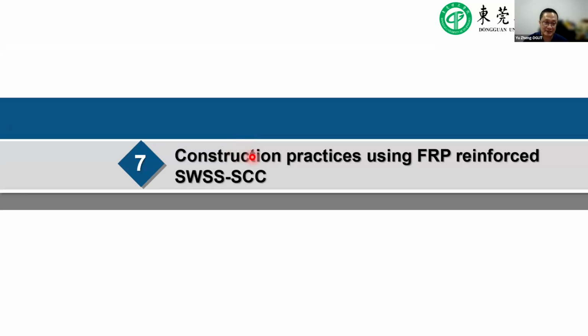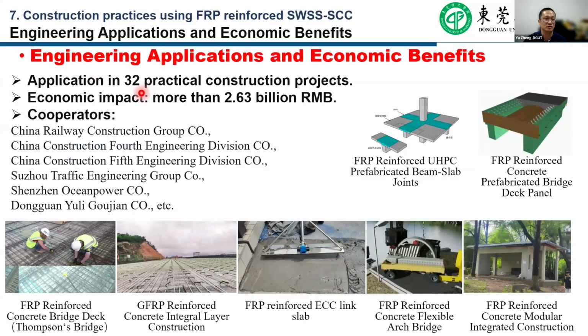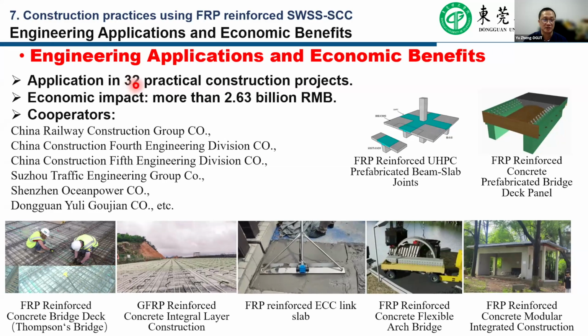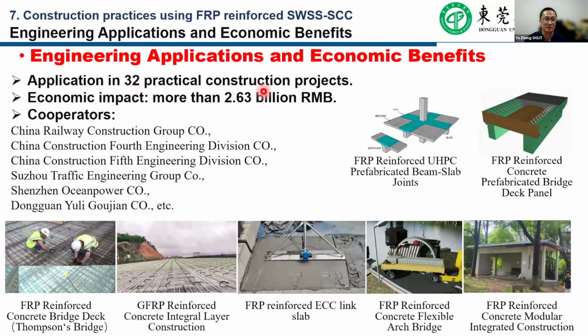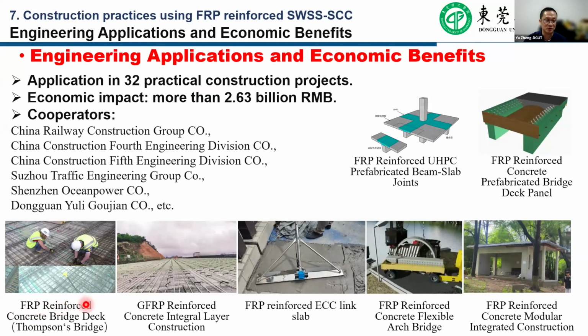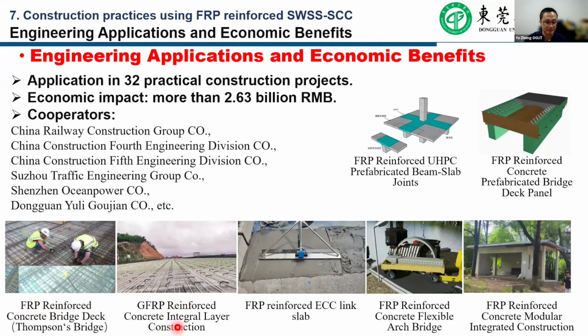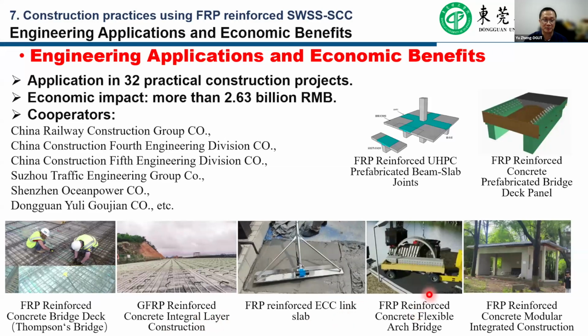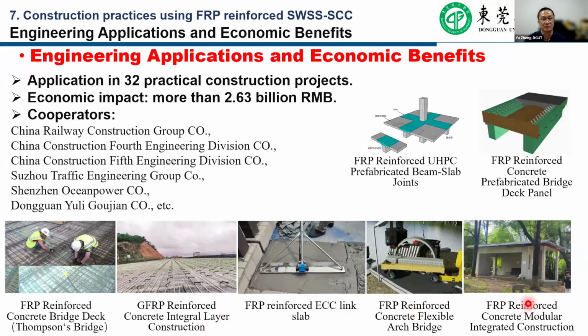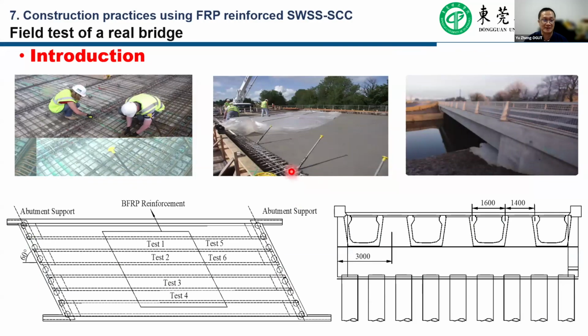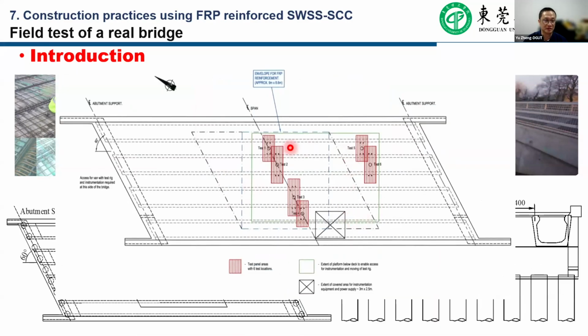And I will take about 1 to 2 minutes to introduce our construction practice. Until now, we have also developed more than around 32 practical constructions, including some bridge deck slabs, some concrete integral layers, some link slabs, some prefabricated structures, and some MIC models. This is one of our tests, in cooperation with Queen's University. This is a bridge built in Northern Ireland. Those 4 panels are for the FRP reinforced self-compacting concrete. This is for the steel reinforced one.